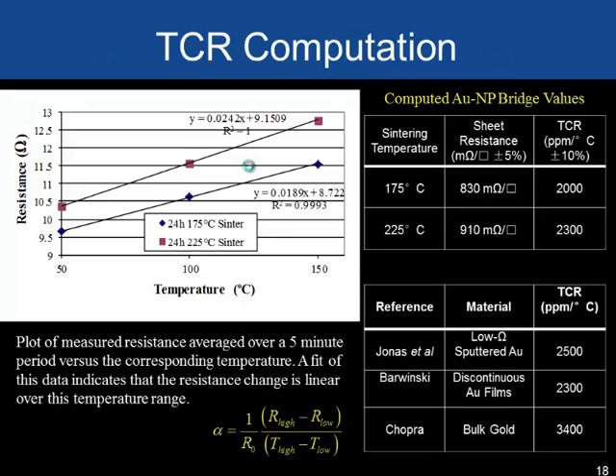If we take our data and average it at our 3 temperatures to compute the TCR, we find for both of our sintered films that a very linear response was observed, and we can compute them as 2,000 or 2,300 ppm per degree C for our measured samples. This is reduced over bulk gold, which is about 3,400 ppm per degree C, but agrees well with similar films, including a low resistance sputtered gold film, as well as a discontinuous gold film reported in the literature. Now, if we approximate the film as rather homogeneous, even though it's highly disordered, we can back out the sheet resistance per the earlier relation as 830 or 910 milliohms per square.